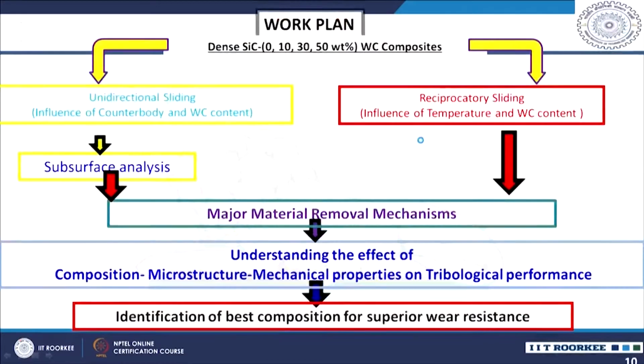So, after Vickers indentation, at the edges of these indents the cracks are propagated, and we can see here when no tungsten carbide was added, the deflections for the cracks are minimal, whereas the deflection or the bridging are actually improved when you have the tungsten carbide particles. So, these tungsten carbide particles improve the fracture toughness by the bridging of the crack or the deflection of these cracks. So, with this introduction of this material,